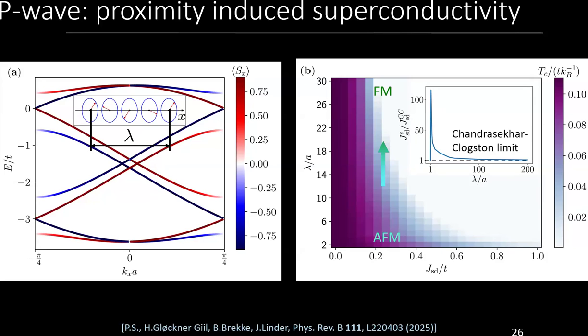Here we're doing numerical lattice calculations, and I vary the period. We start with period 2: spin up, spin down. It's not different from an antiferromagnet, right? Simple. And we can see that there is superconductivity, there is a critical temperature, and it's very robust to the coupling to spins, up to a specific coupling strength. The critical temperature is high, and this means that the superconducting state remains robust towards the introduction of this antiferromagnetic spin order, which is expected. Antiferromagnets are expected to be compatible with singlet superconductors.